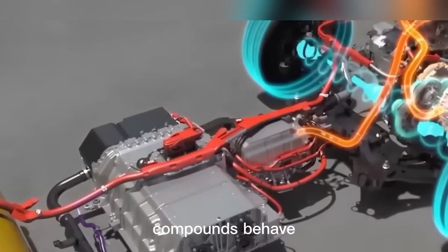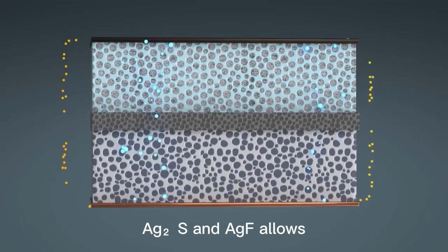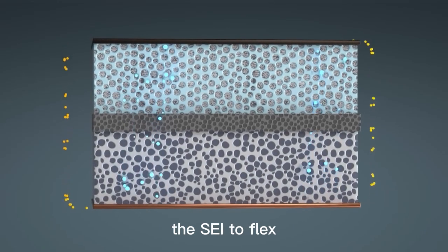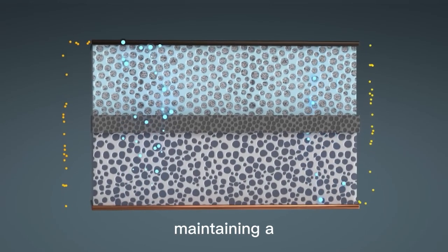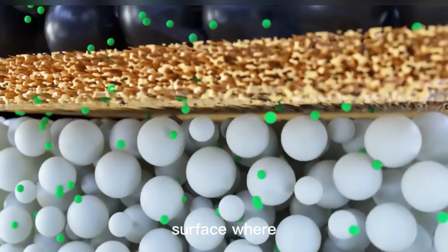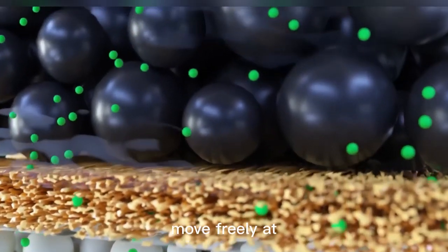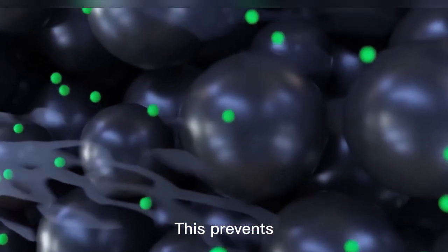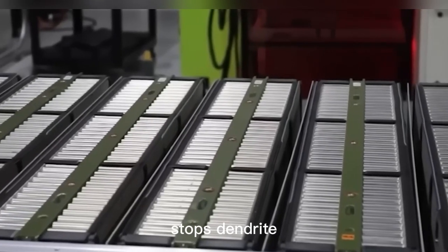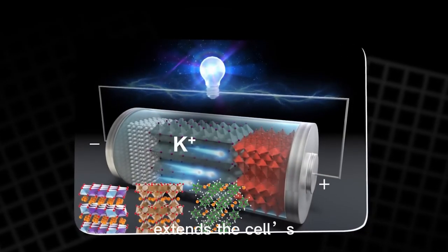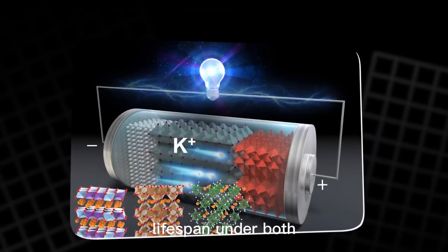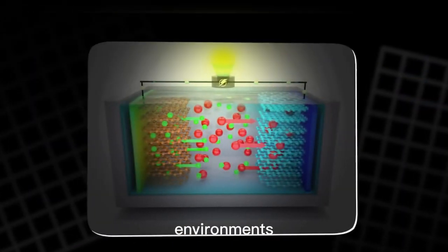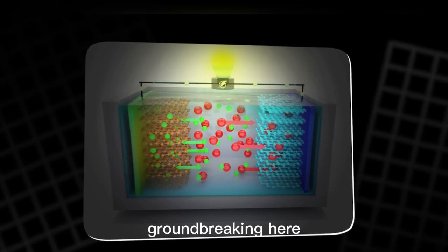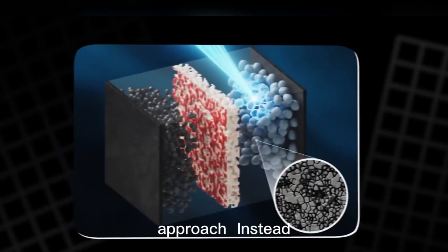The secret lies in how the silver compounds behave. The combination of Ag₂S and AgF allows the SEI to flex without cracking, maintaining a smooth and uniform surface where lithium ions can move freely at consistent speeds. This prevents uneven buildup, stops dendrite formation, and dramatically extends the cell's lifespan under both high current and low temperature environments. What's groundbreaking here isn't just the numbers, it's the approach.